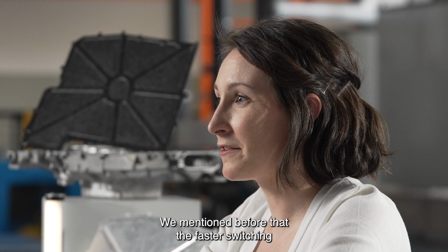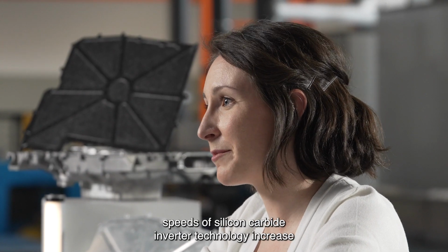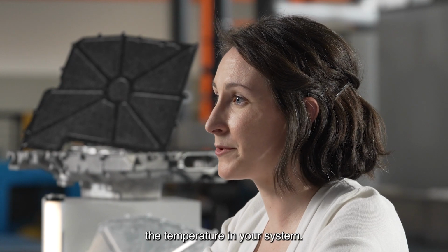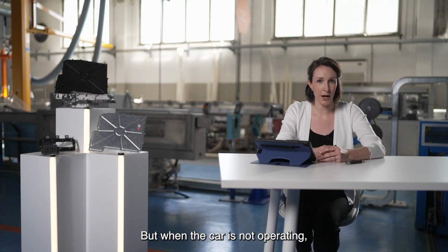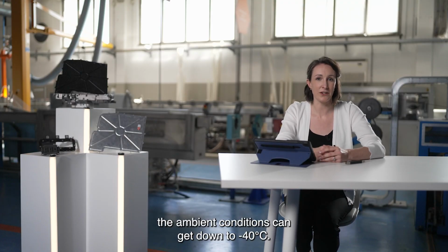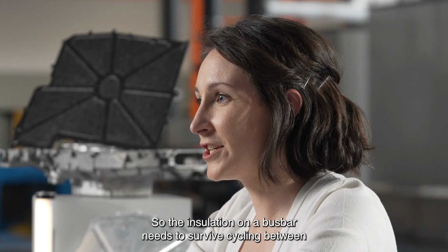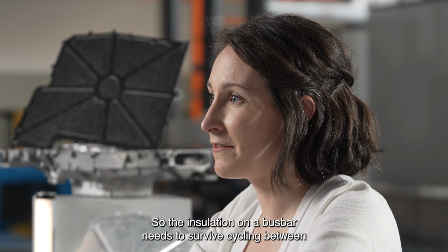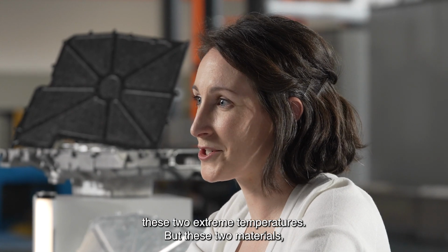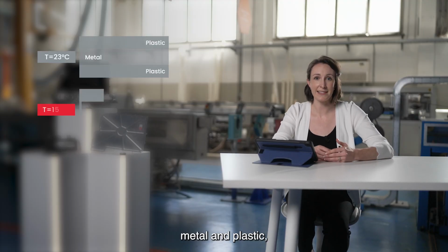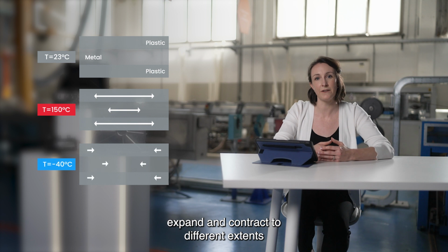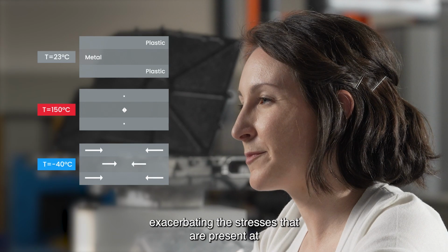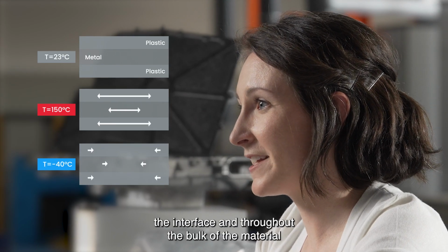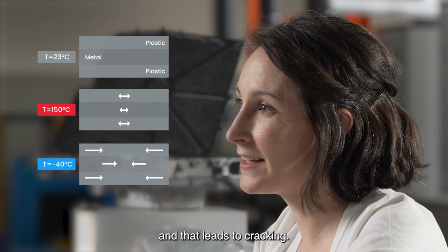We mentioned before that the faster switching speeds of silicon carbide inverter technology increase the temperature in your system. But when the car's not operating, the ambient conditions can get down to -40 degrees C. So the insulation on a bus bar needs to survive cycling between these two extreme temperatures. But these two materials, metal and plastic, expand and contract to different extents during heating and cooling, exacerbating the stresses that are present at the interface and throughout the bulk of the material, and that leads to cracking.